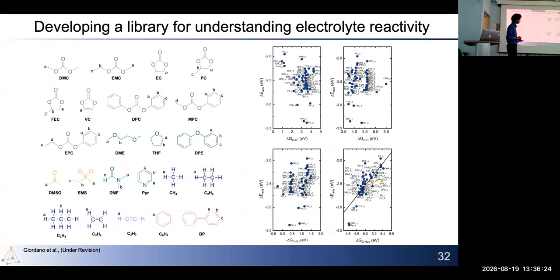On all four of these plots, on the y-axis you have the adsorption energy, how much it takes to break one of the hydrogen bonds on these electrolytes. On the x-axis are the descriptors we're trying to develop, explaining the reactivity of these molecules. What we found is that it's the energy it takes to replace the CH bond of these molecules with a CO bond. If you compute the energy of replacing that CH bond with a CO bond in the gas phase, that correlates with the adsorption energy that happens on the surface.